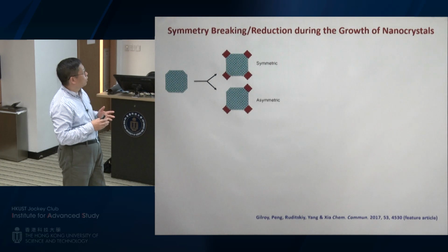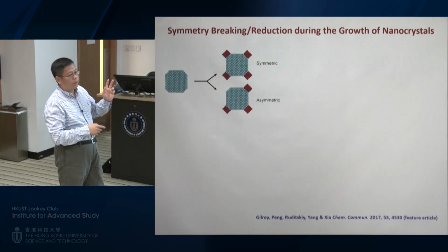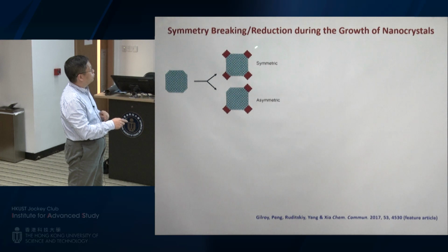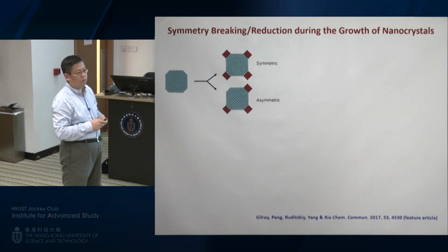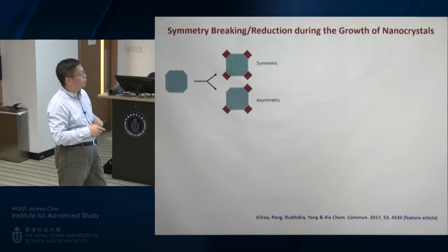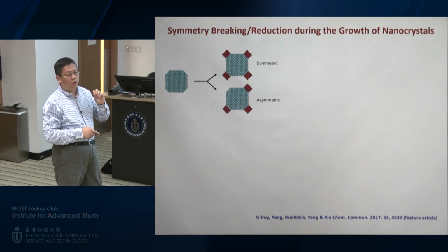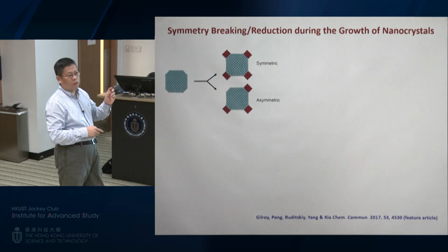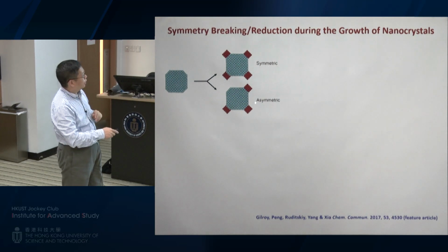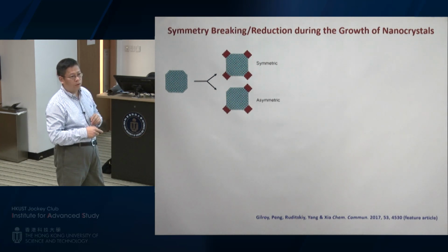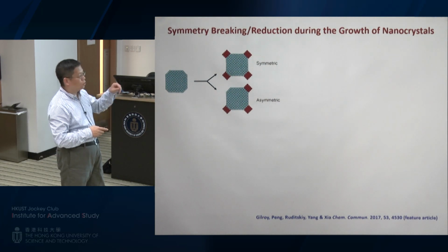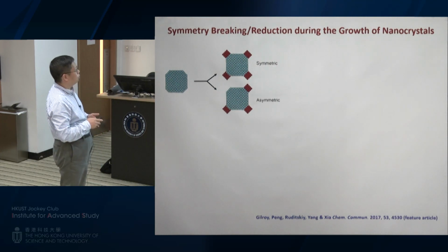So now when they do growth, they have 2 major different patterns. One is symmetrical growth. You are going to have atoms being deposited onto all of these different corner sites. On the other hand, you may also have growth on just 1 corner, or 2 corners, or 3 corners, like shown over here. And this one will have lower symmetry than this one, so that's why this is asymmetrical growth. Okay, and this actually could be manipulated if you control the experimental conditions. Let me show you how we can do it.